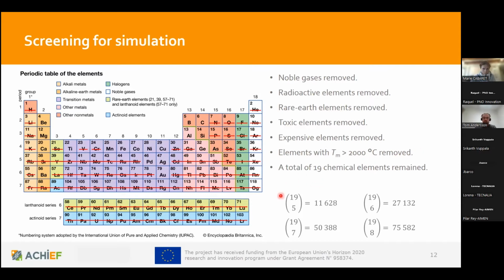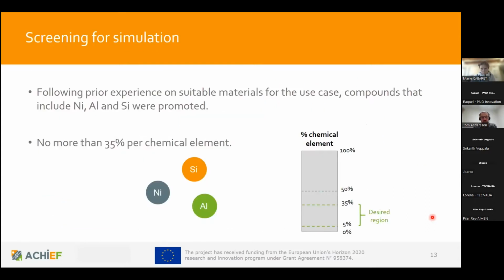And also these rare earth elements were excluded from this second screening. So we ended up with 19 different elements, and for those there are still quite numerous possibilities for different alloys. And also these further constraints were decided on the basis of prior experience, and also on what kind of materials are usable for this kind of use case. So we decided to emphasize these nickel alloys that have nickel, aluminum, and silicon, and also this kind of limitation that no more than 35% per individual element is included in the alloy.